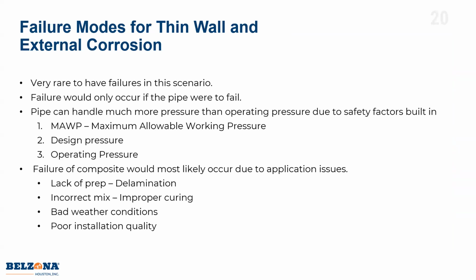But going into failure modes, that's the main thing we want to avoid, and the main thing we want to be prepared for, and make sure we get those repairs going as long as they can, get you to your turnaround, get you to wherever you need to go. So it's very rare to have a failure when you have thin wall and external corrosion. There's nothing really that could happen at that point. The only failure off the top of my head here would be if the pipe were to fail. And the only way the pipe were to fail would be that you're operating at a pressure that the pipe couldn't handle because of how thin it is.